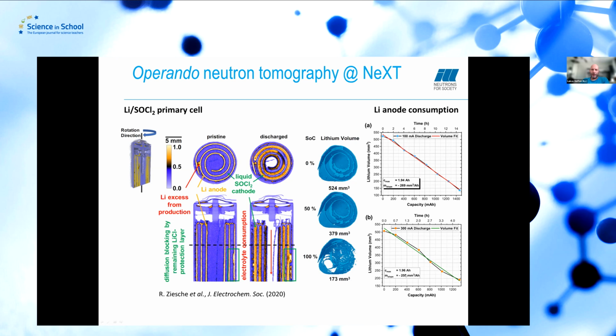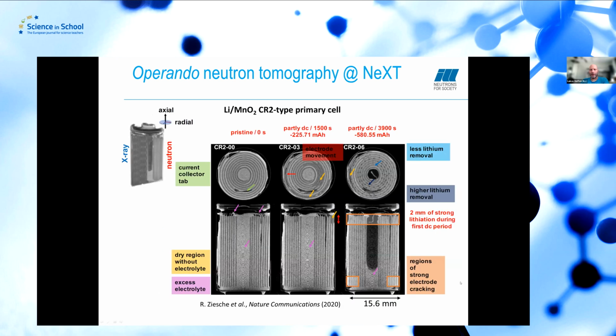You can do that for different currents. For instance, the different discharge currents here are 300 milliampere and 100 milliampere discharge currents, and you get then to something like a capacity of 1.4, 1.2 milliampere hours that you can draw out of the battery. The same here is now for the different materials. The manganese oxide primary cell again, so you cannot charge it; you can only discharge it.